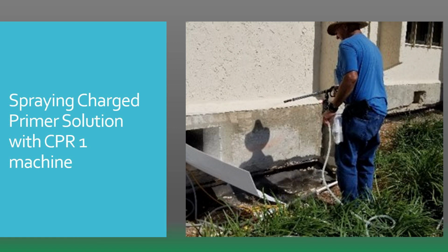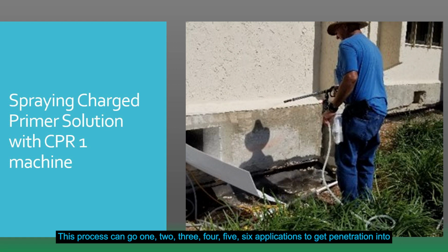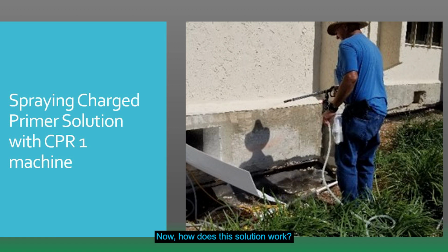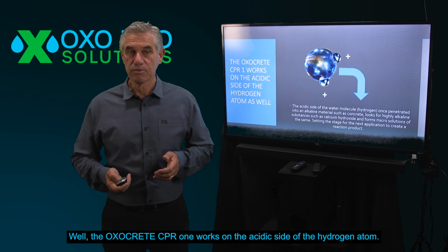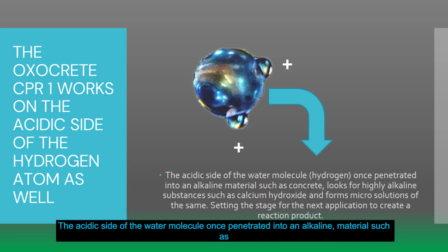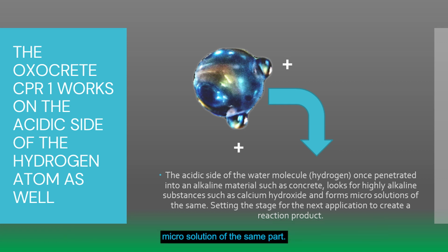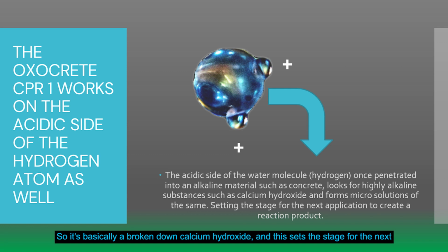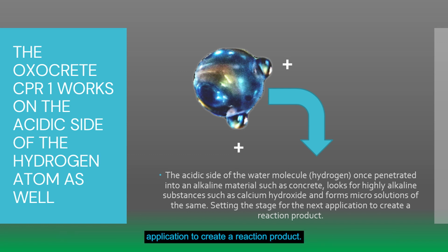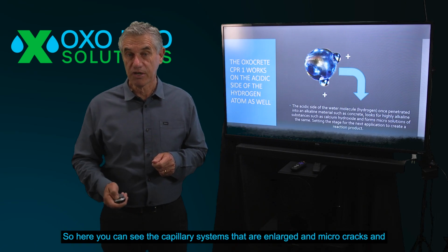We're spraying on what we call charged solution onto a deteriorating concrete surface. This process can go 1, 2, 3, 4, 5, 6 applications to get this penetration into the concrete with this solution. Now, how does this solution work? Well, the OXOCRETE CPR1 works on the acidic side of the hydrogen atom. The acidic side of the water molecule, once penetrated into an alkaline material such as concrete, looks for a highly alkaline substance such as calcium hydroxide, and it forms a micro solution of the same part. So it's basically a broken down calcium hydroxide. And this sets the stage for the next application to create a reaction product. Okay, we're looking to change this into something different.